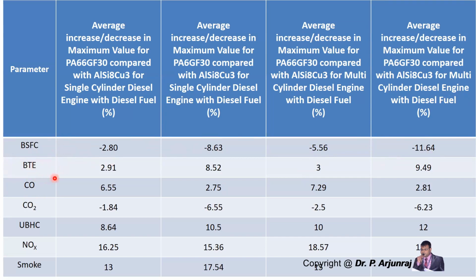And you can also see that brake thermal efficiency is almost 2.91% higher when you compare aluminum with PA66. But when you compare PA6 with aluminum for a single-cylinder engine, you can also find that at maximum you can get 8.52 brake thermal efficiency on the higher side. And the average increase or decrease in the maximum value for PA66 compared with aluminum for a multi-cylinder diesel engine is going to be 3 and 9.49 in the case of brake thermal efficiency when comparing PA6 with aluminum. And these are other comparisons: CO, CO2, unburned hydrocarbon, NOx, and smoke.